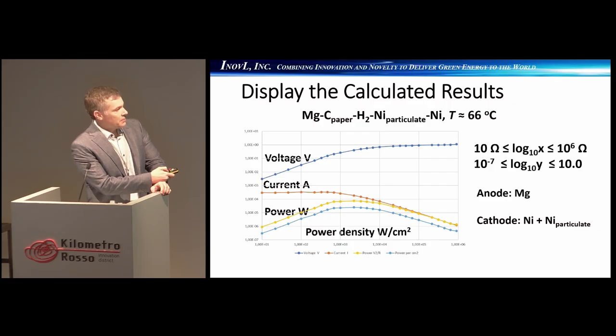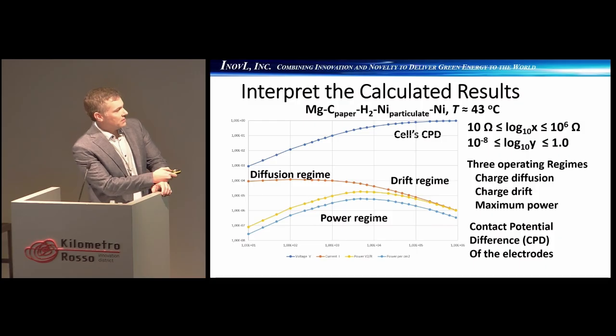So this is a pretty typical LEC cell performance characteristic shape for a LEC. So you have our voltage on top, current, power is the yellow, and our power density per square centimeter. All right, and so one of the things to note is that there are several operating regimes of the LEC. So at open circuit, you have the cell's contact potential difference, and that is your drift regime. At the bottom end of resistance, you have your diffusion regime, and in the middle where they meet, you actually have the power regime where you can reach peak power.